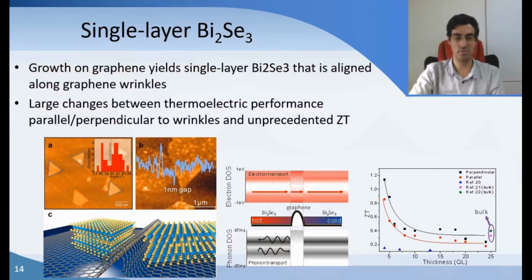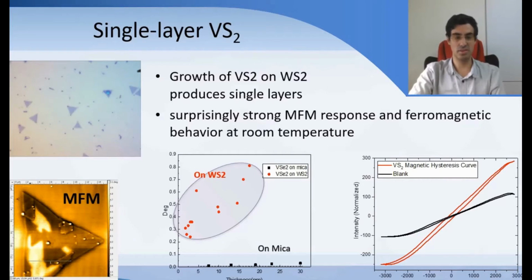The other thing you couldn't do with other substrates is growing ferromagnetic materials. Recently, 2D ferromagnets have been demonstrated, but we're the first ones to grow single-layer vanadium sulfide, and we're growing it on both tungsten sulfide and on mica. Mica is a crystal whose structure is pretty conducive to epitaxial ordering of vanadium sulfide. Tungsten sulfide also has a comparable lattice structure. So both of them are producing epitaxial alignment. You can see that in the OM image. Within a tungsten sulfide grain, the vanadium sulfide grains are aligned.